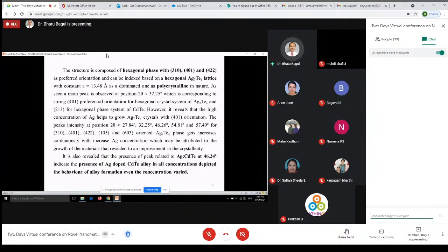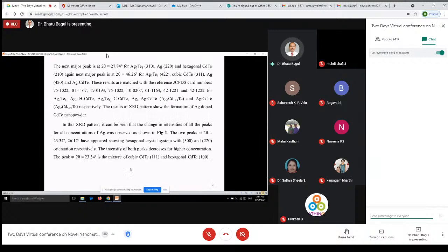Therefore, it is revealed that the presence of a peak related to Ag CdTe at 46.24 indicates the presence of Ag doped CdTe, alloy formation in all concentrations, even when the concentration is varied. That is, as the concentration is varied, one of the peaks is always there which contains the Ag doped CdTe. Therefore, we can say that the Ag is doped in the CdTe.